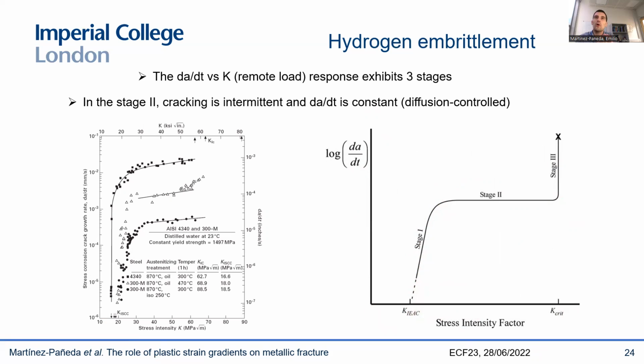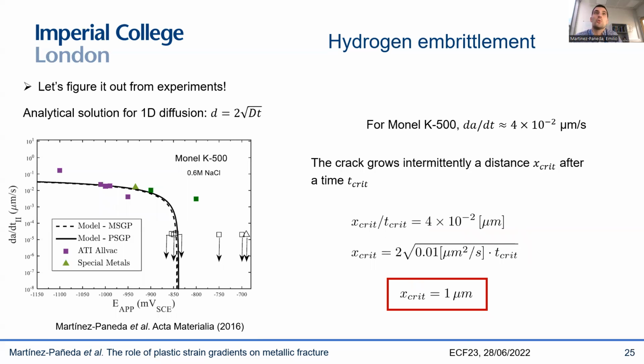Your crack can only grow whenever the hydrogen has had enough time to reach the critical distance ahead of your crack. So the crack is effectively jumping whenever the hydrogen has reached the critical distance. Since we know from the experiments what the crack speed is, for example, for this nickel superalloy, we know that it is probably 0.04 microns per second.